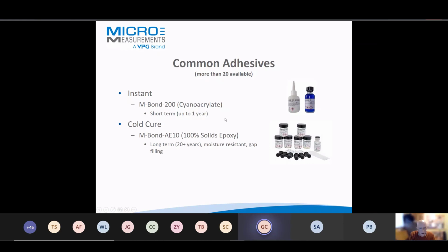We have cold cure adhesives. So 100% solid epoxies, for example, are really good for long term. They're moisture resistant and they're good at gap filling and textured surfaces. So you can bond to concrete, rocks, pre-preg composites, that kind of thing. They will fill those gaps, whereas a cyanoacrylate will not fill the gaps.